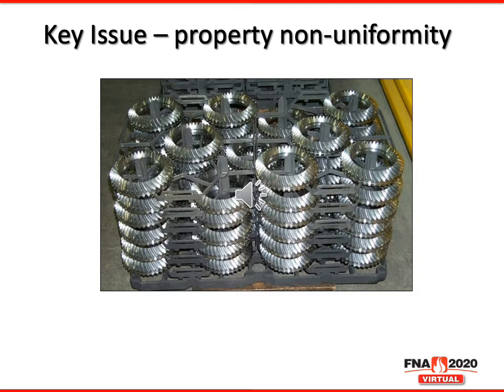The reason distortion is an issue is because of property non-uniformity. Well, what do I mean by that? Well, I mean that in each batch, parts are arranged to maximize the use of the furnace. They're positioned in the furnace like is shown in the photo, where they're close to one another, and the flow of the quenching media has to go through the batch.